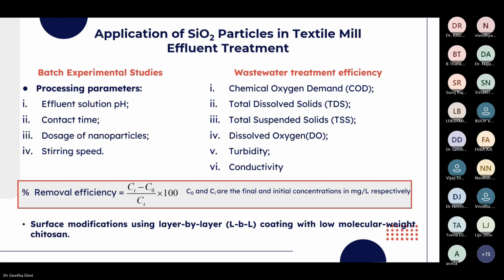So these silica nanoparticles we have tried for the treatment of textile industry wastewater. Batch experiments were conducted by varying the processing parameters of the effluent solution. pH was varied from acidic to alkaline range. Contact time was varied. Dosage of nanoparticles and stirring speed were varied. After the treatment, the efficiency of the wastewater treatment was monitored by measuring COD, TDS, TSS, dissolved oxygen, turbidity and conductivity, and the percentage removal efficiency was calculated